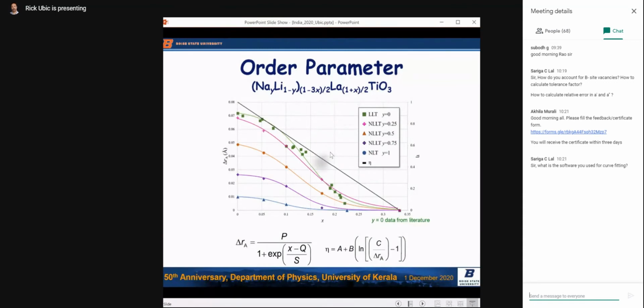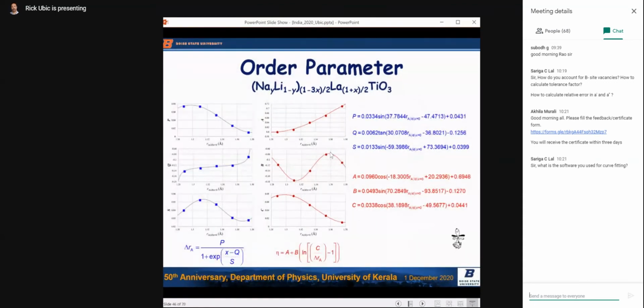generally, and we can. Again, lots of coefficients involved, so you'll have to forgive me, but it works. Again, they're not all independent either. I think you can tell that. So we have delta RA equals this, and the important thing here is the ordering parameter generally is this guy, and the ABC coefficients come from here. You just stuff in the ideal A site size for the x equals 0 composition. So these you can plug in right away. These are just constants, and out pops the ordering parameter for any A site ordered material, as long as you know the delta RA that is required.